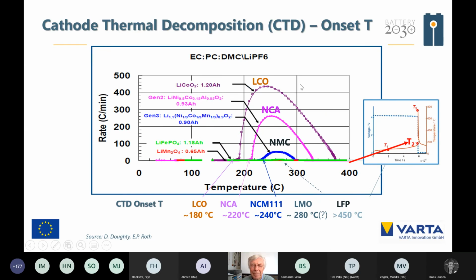But the thermal decomposition temperature, that means T2, depends on the chemistry. We have here ARC measurement, so the heat rate is measured via the temperature. What you could see, the LCO started, that is the T2, at 180, NCA 220, NCM111 240, LMO about 280, LFP 450 centigrade. So that means these materials are more temperature stable than the layered materials like NMC and NCA. What is the reason for that?